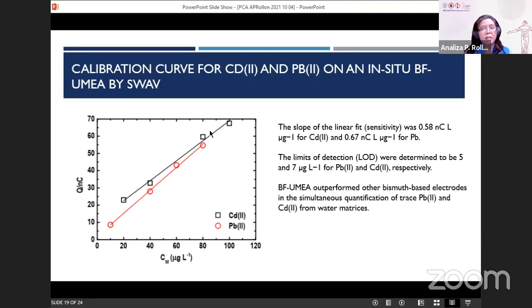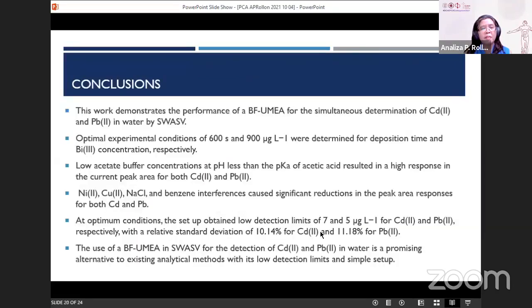And then we were able to determine the slope of the linear fit, which gives us the sensitivity, as 0.58 for cadmium and 0.67 nC per microgram per liter for lead. The limits of detection were determined to be 5 for lead and 7 micrograms per liter for cadmium. And this actually outperformed other bismuth-based electrodes in the simultaneous quantification of trace lead and cadmium from water matrices.